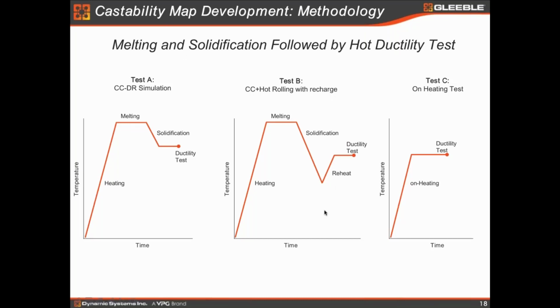And the second one is to simulate really the hot charging. So we still do the casting, melting, and the solidification, but we cool the sample down to a certain temperature before the billet goes into the reheat furnace, as we do. So we cool down to a certain temperature and reheat it to another temperature. And actually in some of the CSP mills, they have a tunnel furnace. They are reheating either the edge of the slab or the slab itself, doing so also. So you can use this way to simulate whatever you've seen.